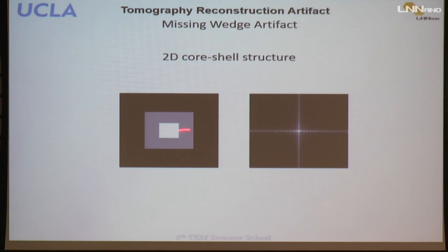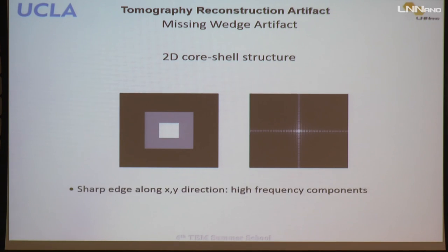usually has to have very high frequency information. To make the sharp edge from the Fourier transform, you have to have a lot of high frequency data points to create the sharp edge. So that's shown here. Along this sharp edge direction, you see high frequency peaks in Fourier space. So when you reconstruct this object using filter back projection